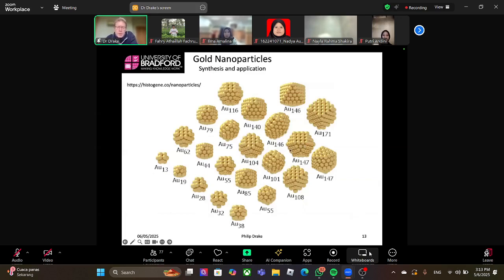So the gold clusters are actually lumps of gold atoms. We start with the smallest, Au13, and get up to bigger sizes, Au147. This is a computer simulation of what different nanoparticles could look like with different numbers of gold atoms. It's about 0.6 nanometers. So these particles here are all less than 1 nanometer. This is 1.8 nanometers. These are still very small nanoparticles, about 2 nanometers in size.